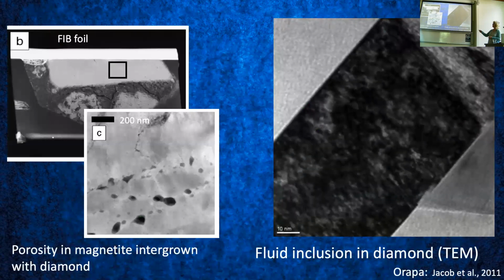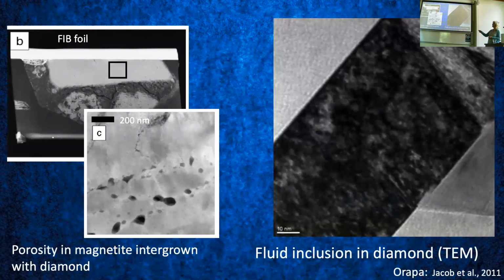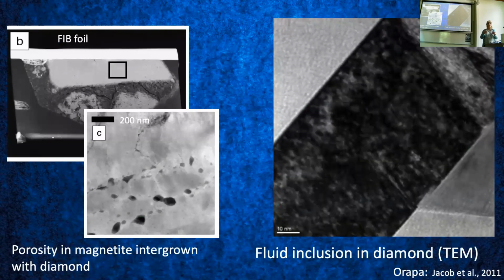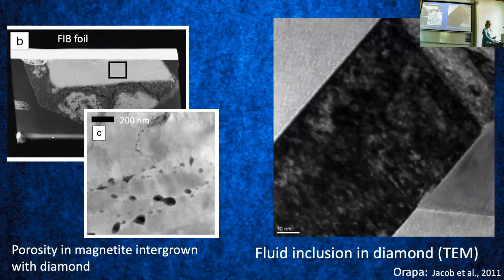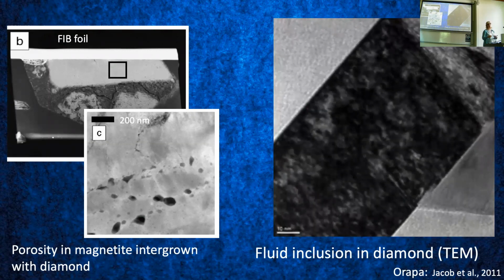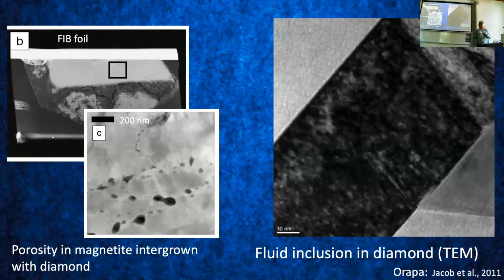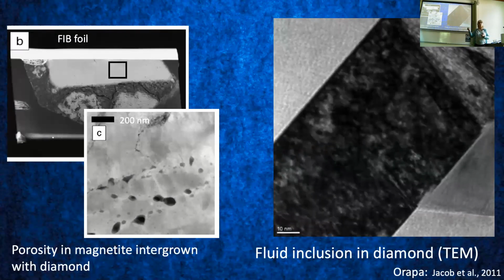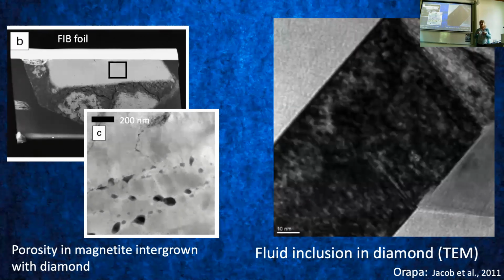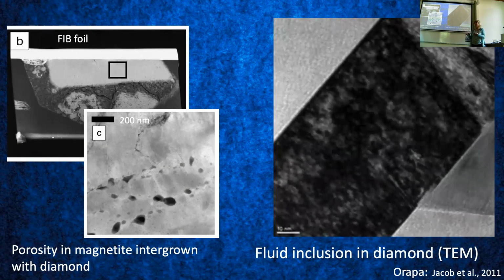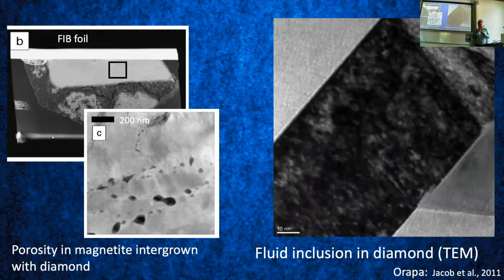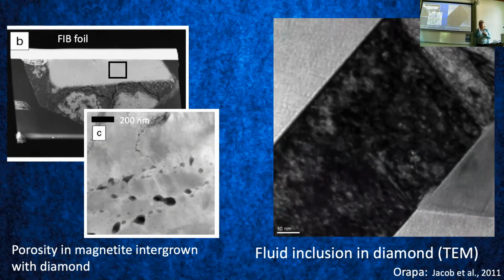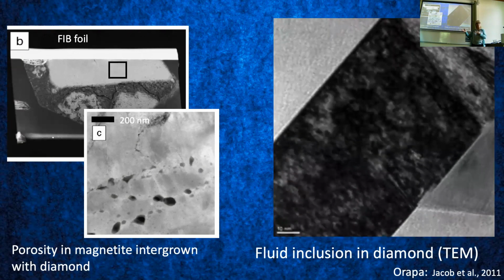This is an alteration rim, which is a mixture of oxidized phases and some phyllosilicate, which is a late-stage history of this sample. It also highlights the problems, because unlike in gem diamonds, where the inclusions are shielded by the diamond and you are sure you have pristine information, in these rocks it's intergrowth most often, and they're open to the environment, and you can actually get metasomatic effects. So you have to sit down and deal with each sample and figure out what is primary information and what is secondary information, and have some checks and balances around this.